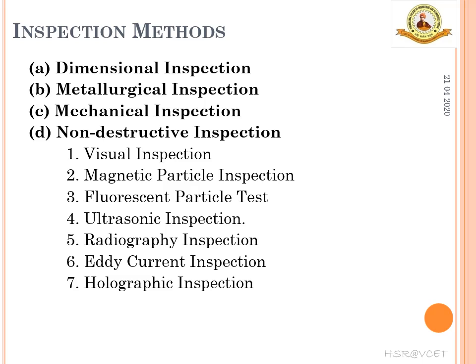For dimensional inspection, instruments such as micrometers, automatic gauges, etc. are used to check the dimensions of the parts against the drawing. For metallurgical inspection, specific equipment like disc sectioning machine, specimen mounting press, grinding and polishing turntables, acid-etching capabilities, and an optical metallurgical microscope with magnification capacity are required. Weld shape, discontinuities, and metallographic phases in different areas of the weld and cast metals can be obtained by this method.